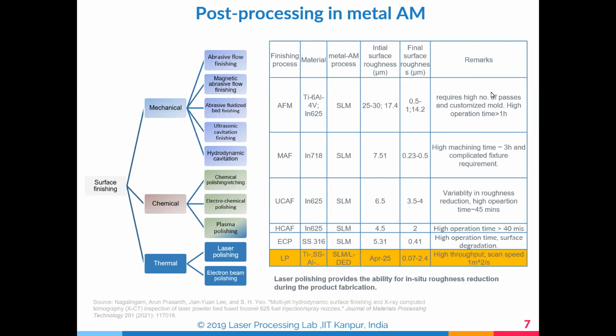When we talk about remarks, you can see that it requires a higher number of passes. What I'm trying to say is, if you are doing AFM, the abrasive flow machining process, the number of strokes is called the number of passes. It takes more than 1 hour, or 3 hours. UCAF takes 45 minutes, HCAF takes more than 40 minutes. And when we talk about LP, which is laser polishing, it is very fast, very smooth, and gets the best out of it. Okay, so these are all the processes.